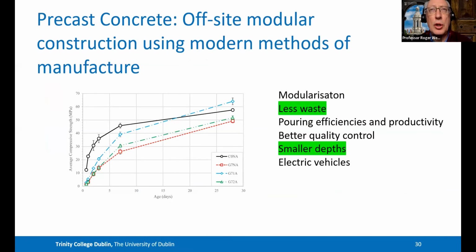But when it comes to precast use, the use of supplementary cementitious materials is not favored for productivity reasons. If you need to strip your formwork and cut your tendons at 20 hours or 22 hours, then the slow strength development of most of the SCMs, such as slag and ash, is a disadvantage. So we have to find a way of devising an admixture, which I know people are working on, which accelerates the strength of these supplementary materials to encourage precasters to use it more. Also, with the better quality control in a factory environment, I think they can get away with lighter structures and smaller depths, and indeed promote the use of electric vehicles for the delivery and erection of precast. So all of this will help in reducing the carbon.